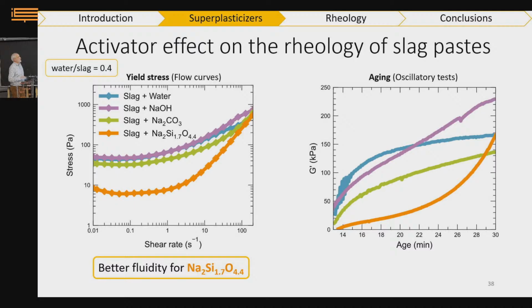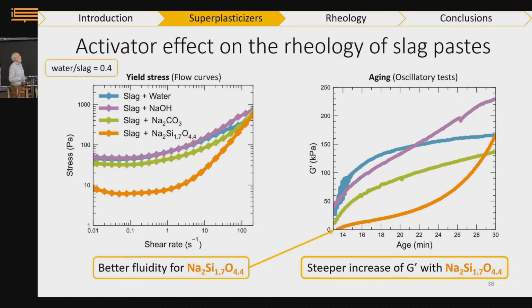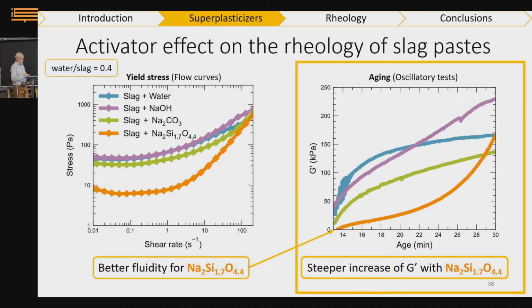You see that for just a suspension of slag in water, or a suspension of slag in water with carbonates or with hydroxide, the shape of the curve remains more or less logarithmic. But for silicate, you can adjust the curves as you want. You will never fit a logarithm to this growth, okay? So something else, something very different, is happening here. So what is the source of this steep increase? How can we understand it in terms of alkali activation, and why is it important?